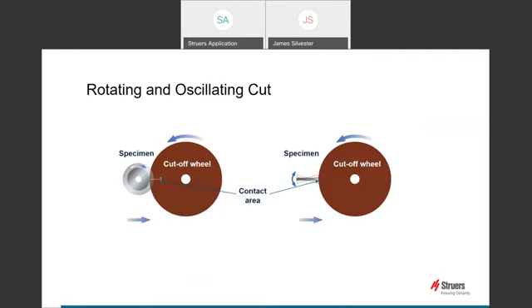On a precision machine, the contact area is always smaller than on the larger machines. This small contact area can put a high pressure on a localized area, but due to the thin cutting wheels used on the precision machines, we need to ensure that we do not rush the cutting operation, as this can easily break a blade.